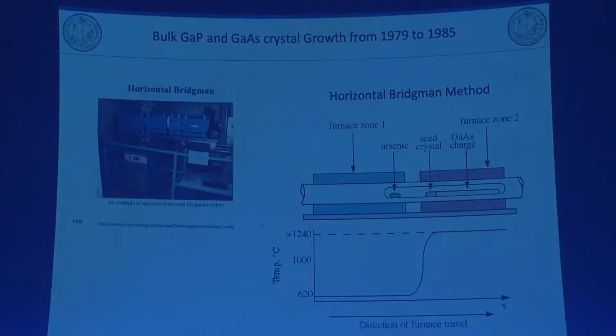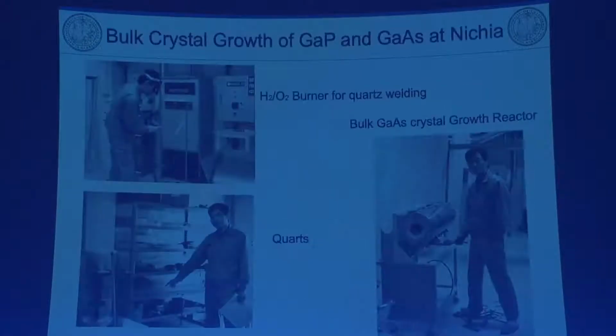temperature to around 1,000 degrees, an explosion happens. Every month I got an explosion. This explosion is so big, it's like a dynamite explosion, because for gallium phosphide we use phosphorus, and the phosphorus used for source material is an explosive material. And arsenic also, we had explosion. In this case, arsenic is a very toxic material. So you can see, this quartz is a big one. This is a hard time, with this burner and welding. And every month an explosion. At that time, I thought my life is over.